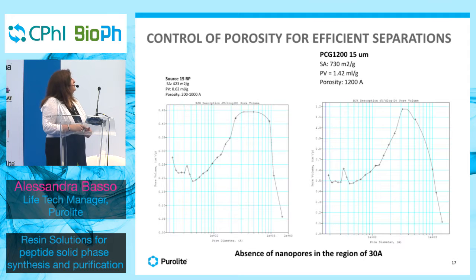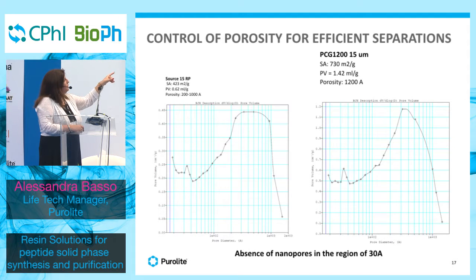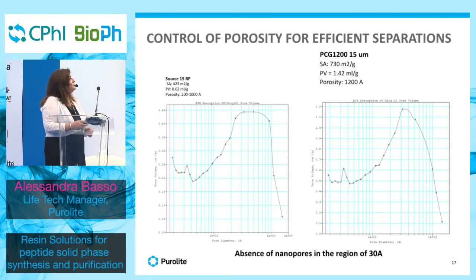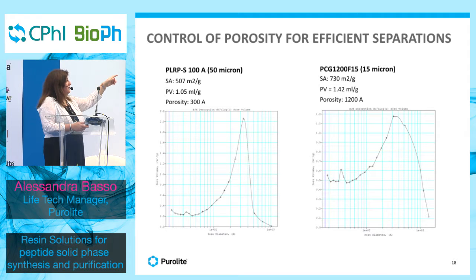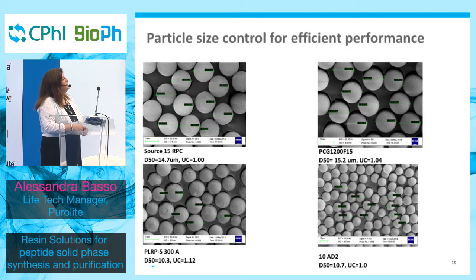Here I want to show you some data on how we control the porosity for efficient separation. Here we compare our PCG divinylbenzene resin against the material that has been on the market for many years, the Source 15RP. You see the profile of porosity. The PCG 1200 has a narrow porosity range, and this allows a better separation because you exclude some molecules, whereas in the first case, you have a broader porosity range. This is another comparison, again with the PCG 1200, with a synthetic material that is quite comparable in performance. And this is how the beads look after making this jetting, or another technology that we call seeding. So you get a product that is very uniform. You see the uniformity coefficient. Probably you are not familiar, but the UC that we measure is a measure of the deviation from the middle of the Gaussian curve that you get. The closer to 1, the better the product.